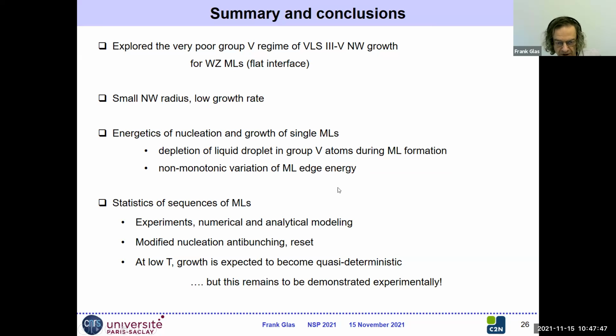And then we have gone to sequences of such monolayers, and we have compared the statistics of these sequences between experiments in NanoMAX and calculations, which can be numerical and analytical. So in this case, there's modified nucleation anti-bunching, because after nucleation, the liquid goes to equilibrium, so the nucleation probability is 0. And we have a kind of reset of the system. And this reset is the reason why we may expect quasi-deterministic growth, where the time periods between the completion of monolayers would be strictly fixed despite the random nature of nucleation, at least at low temperature where this option does not operate. But this regime remains to be demonstrated experimentally.